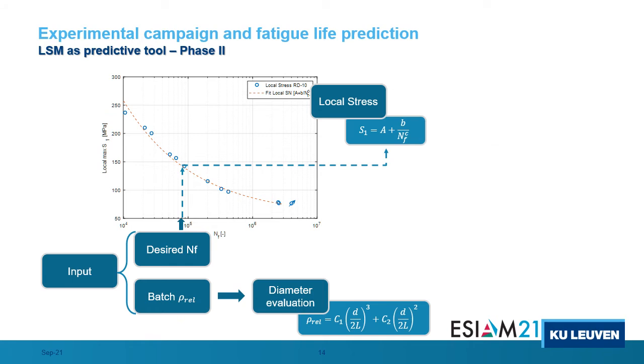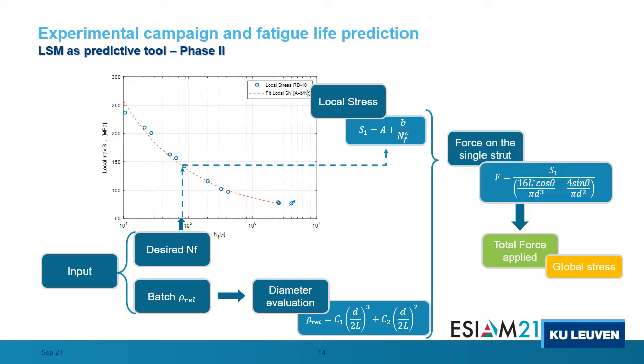This slide presents a schematic representation of how the local SN curve can be used as a predictive tool. In order to obtain the fatigue performances of the other two batches, RD20 and RD30, we use as an input the measured structural relative density to calculate the average strut's diameter using the Gibson and Ashby relation. Combining this information with the local SN curve, it is possible to calculate the force on each strut by reversing the local stress method formulation. Given the total number of nodes, it is finally possible to evaluate the total applied force as a function of the number of cycles to failure and, consequently, the global SN curves for RD20 and RD30 coupons.